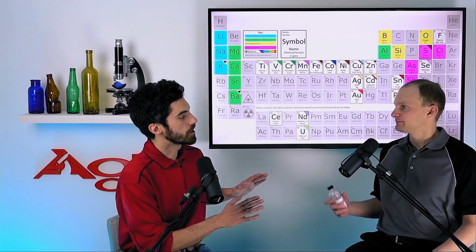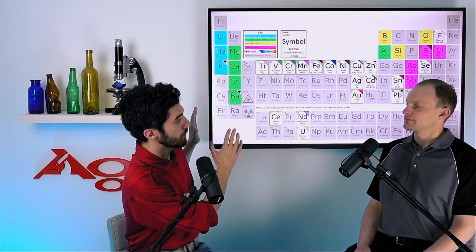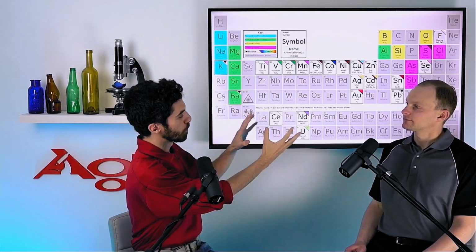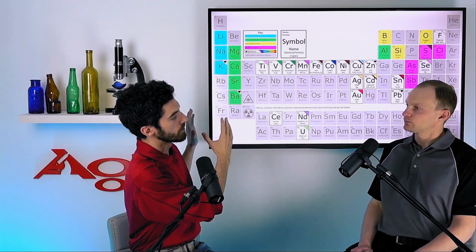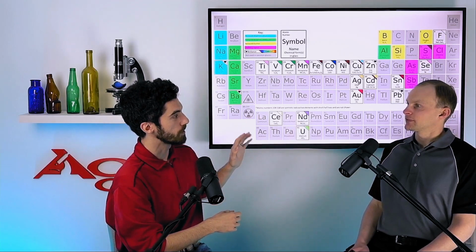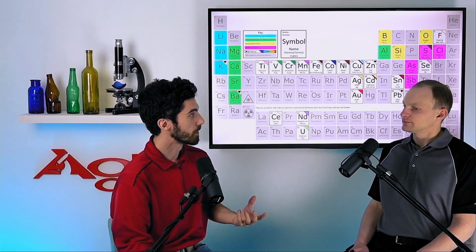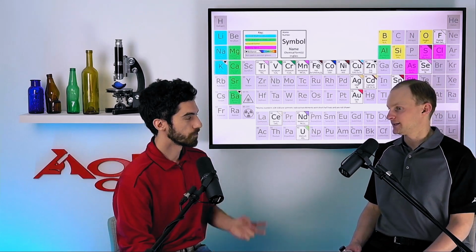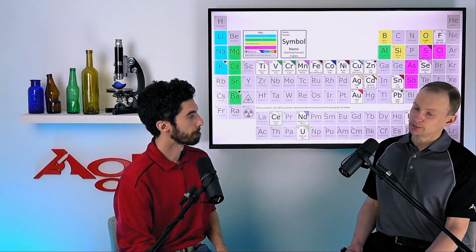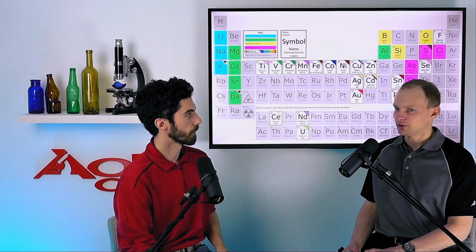So you say it's a decolorizing agent. So what we're doing is taking the opposite end of the spectrum of color and pulling it towards that side. Right. So it's not necessarily that we're coloring it to be pink, we're just pulling it away from that green, and we get into that neutral territory of the flint glass that we're trying to achieve. Yes, we're going to shift our glass to a neutral gray, which is so faint your eye can't see it. Your eye could detect a little bit of green when it's there, but that little bit of grayish color, you aren't going to see.